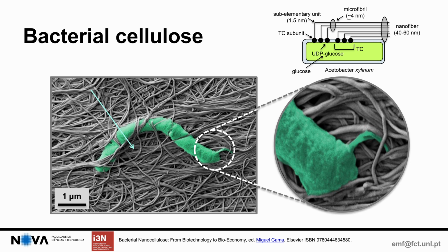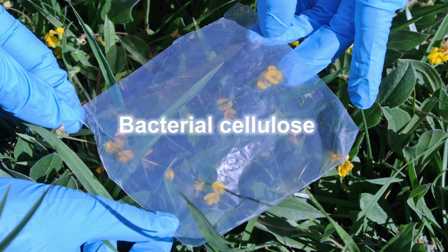Depending on the culture, they are extruding these fibers of cellulose, but since the diameter is so small, of the order of nanometers, we call this cellulose nanocellulose. And in fact, since the fibers are at the nanoscale, we don't have interaction with visible light with this material, and the membranes produced by these bacteria are transparent, as you can see in this image.